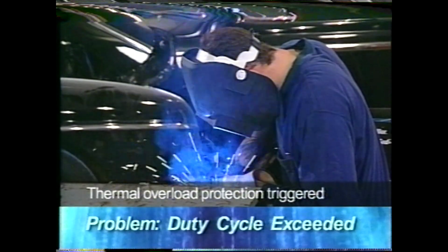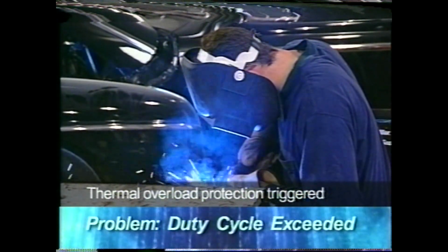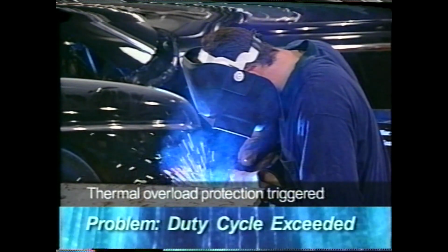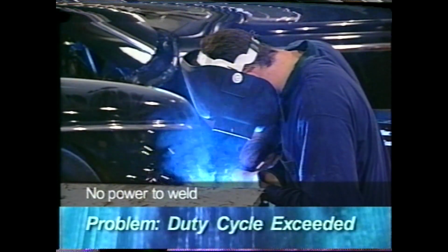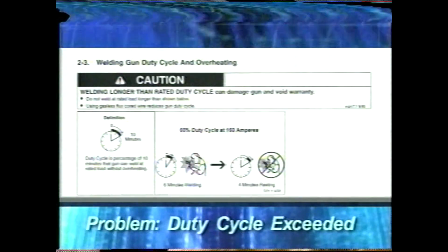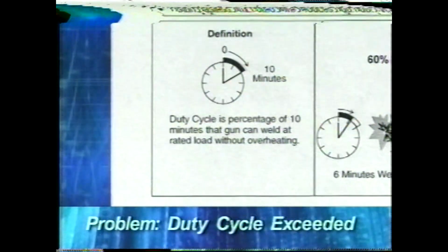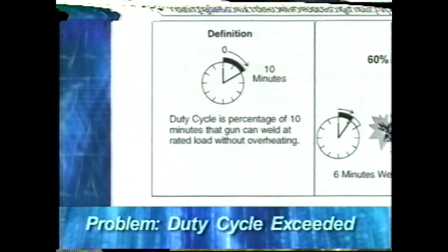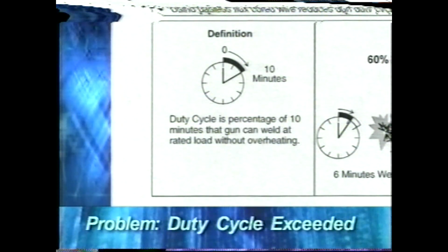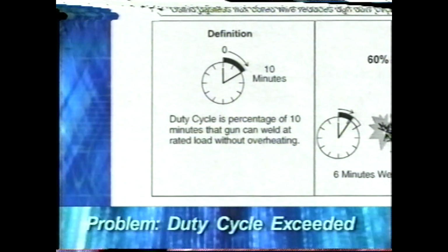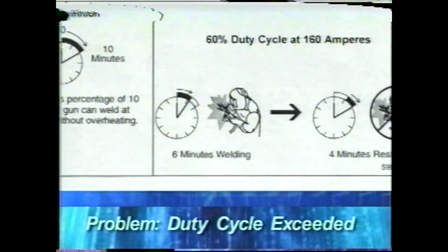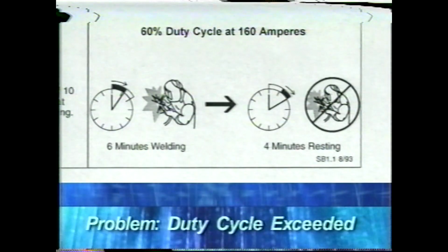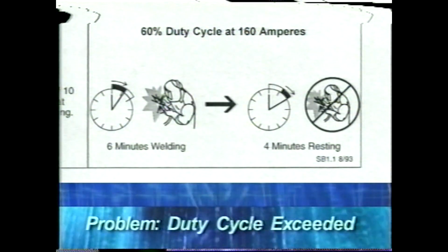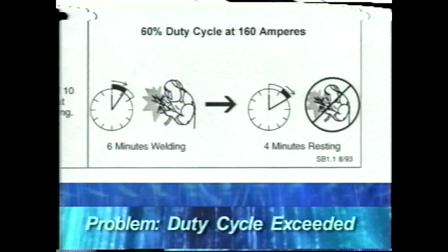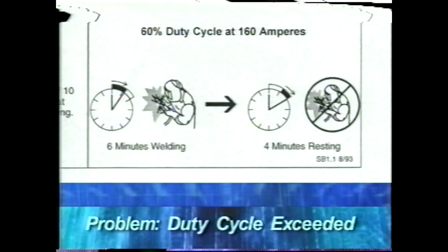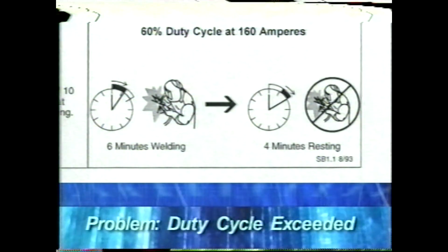All Millermatics are equipped with thermal overload protection, so that if the duty cycle is exceeded, the weld circuit is de-energized to prevent damage to the power source. The duty cycle of each machine determines how long it can be run in a 10-minute period at its rated output before it must be allowed to cool, and it varies from model to model. For example, a machine with a 60% duty cycle at 160 amps can be run at 160 amps for 6 minutes and then must be allowed to rest with the fan running for 4 minutes.